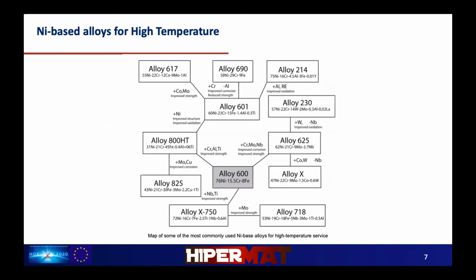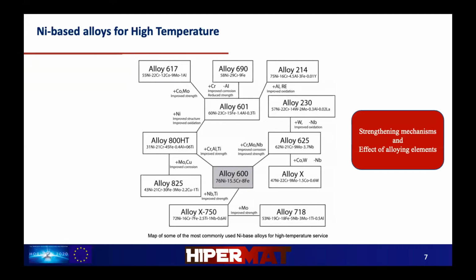Moving further on, here is a map of some of the most commonly used nickel-based superalloys for high-temperature service. In this map, the plus signs denote the addition of elements, whereas the minus sign refers to the removal of elements. As we can see, the different strengthening mechanisms and effects of alloying elements on the final properties of the superalloy. For example, if we consider alloy 600, on addition of chromium, molybdenum, and niobium, we achieve alloy 625 with improved corrosion resistance and improved strength, and so on.